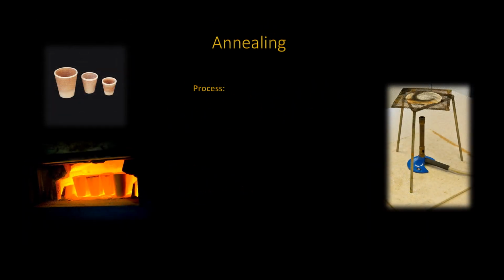Now that you have that amorphous bead, it has to be annealed. This should be the final step if all goes well. Annealing will transform that porous bead and any fine particles into one solid mass. It will also develop that nice shiny yellow color. On inspection, any impurities will be easily and readily seen.